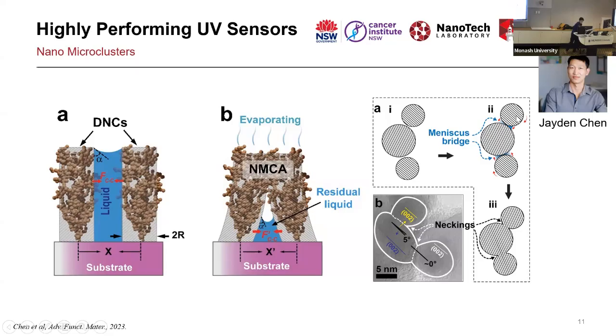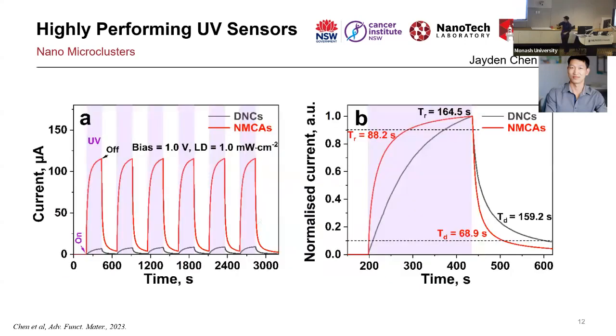Again, this is what we believe. When it is evaporating, the liquid is also sitting in the gap between the particles, and the same scenario is valid there. That liquid, which is ethanol, is evaporating, and it's pulling these 2 particles into each other and cold welding them. Based on the size of the particles and the droplet, we calculated what force or pressure is applied on those particles. It is on the scale of gigapascal, and that is enough to weld, at least in this case, zinc oxide nanoparticles into each other. So we can skip the annealing process, which means you can do it on any type of substrate or nanoelectronics. You don't need the post-sintering process to make your electrical connection happen. What I'm going to show you here is that we use it as a UV sensor, which is one of our applications. The bottom one in black is UV on, UV off, UV on, UV off.